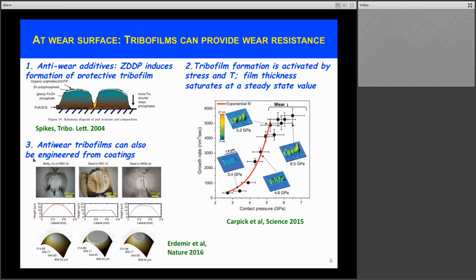that in fact coatings can be designed so as to promote the formation of this tribofilm. So now you can control the formation of the tribofilm not through an additive that's added to a lubricant, but by designing a coating that promotes the formation of the right tribofilm. Here, copper or nickel are incorporated in a molybdenum nitride coating so as to promote the formation of a diamond-like carbon tribofilm at the interface.